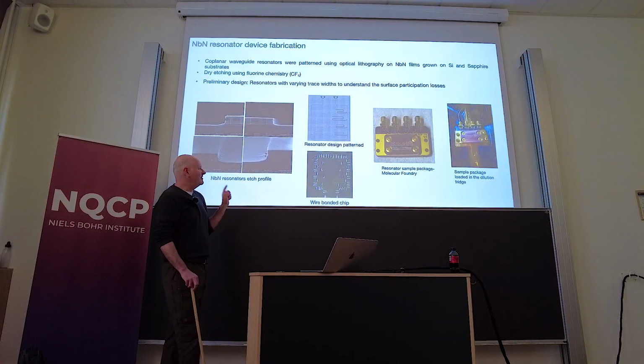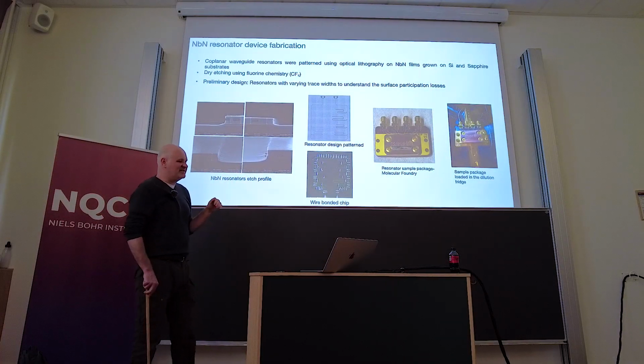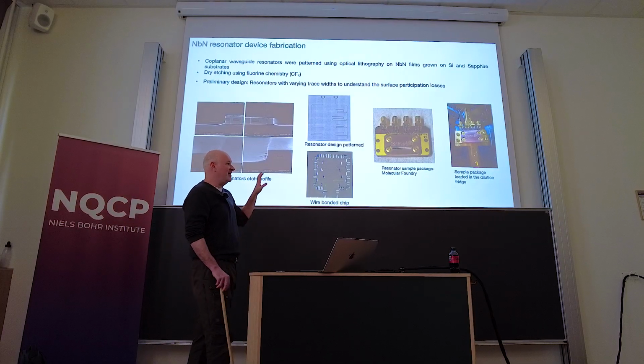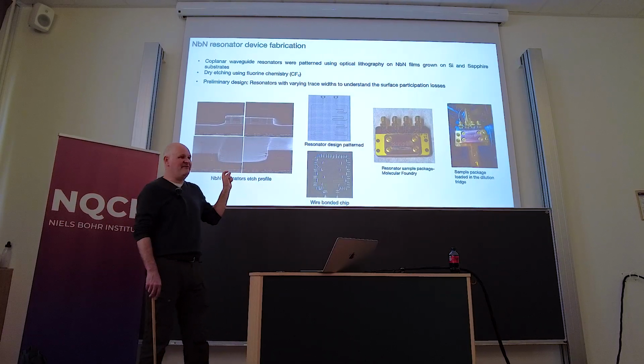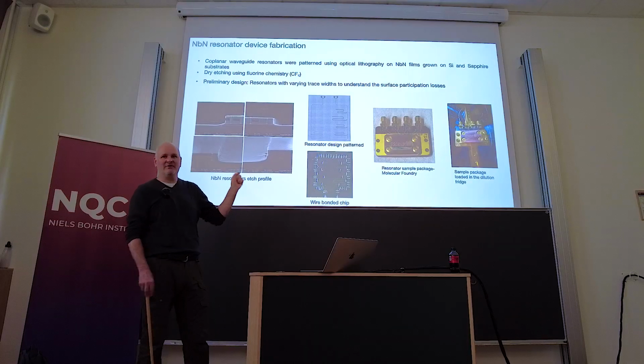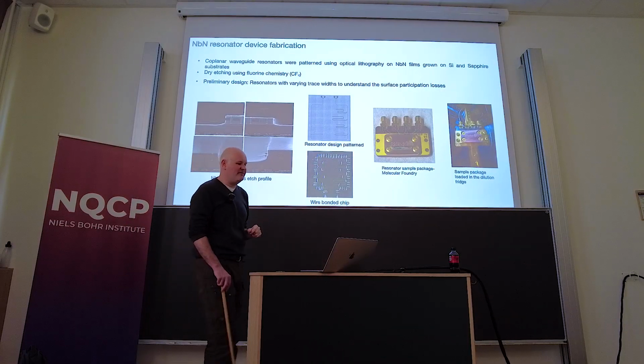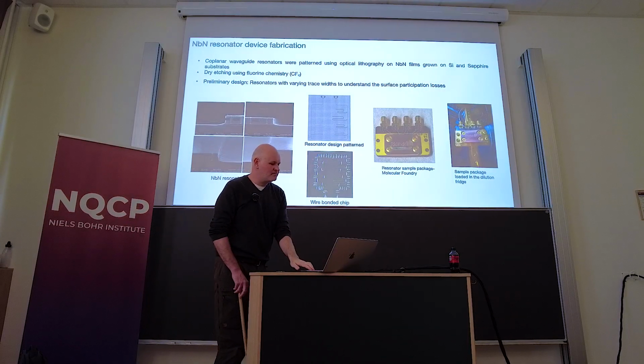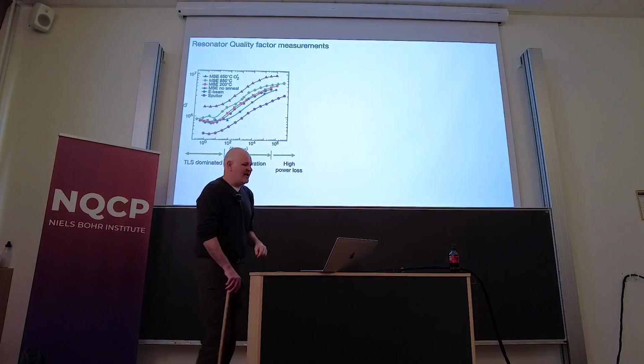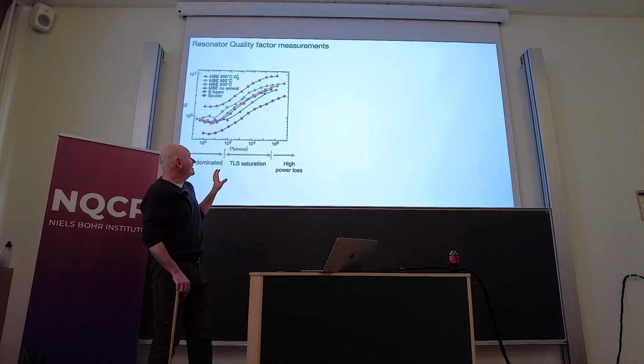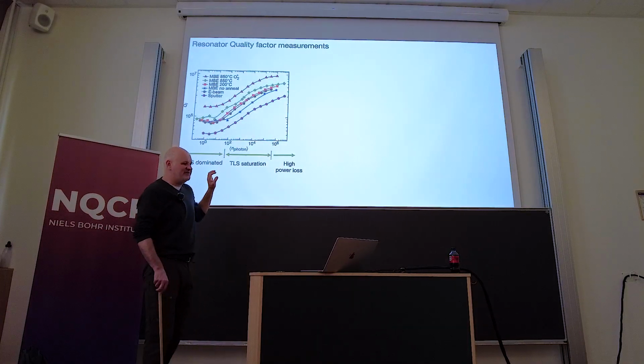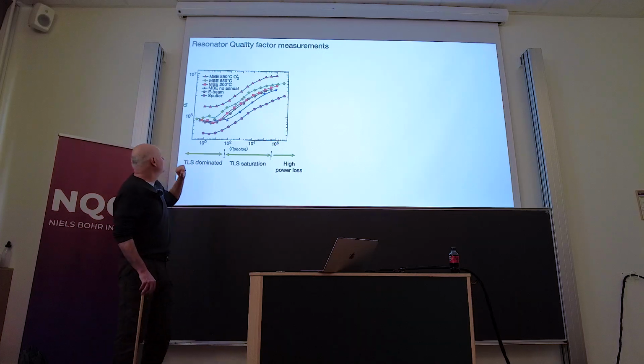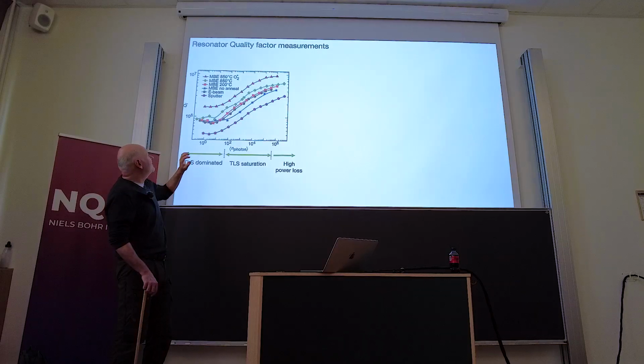Then with those materials, we fabricate resonators. So these are identical to the aluminum resonators, but modified just to get frequencies in the range that we want, because the frequencies are different in niobium nitride than aluminum. And I just wanted to throw this up quickly to get everyone on the same page. So this is not our sample. This is what you expect to see for these resonator quality factor measurements. They always have this sigmoidal shape.